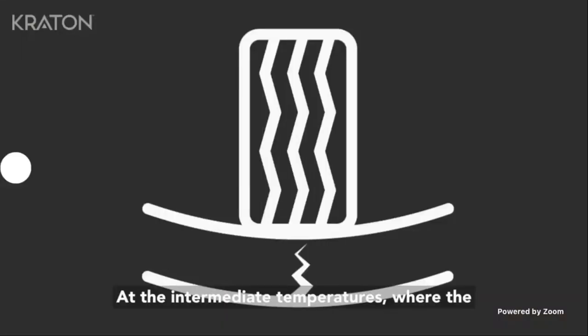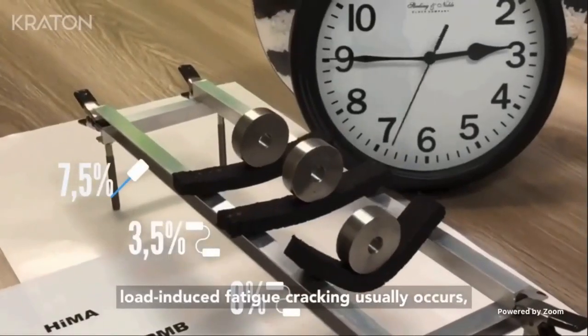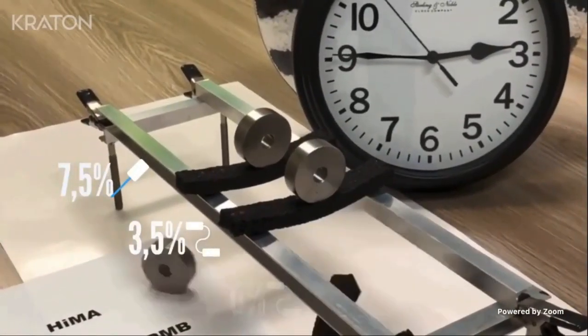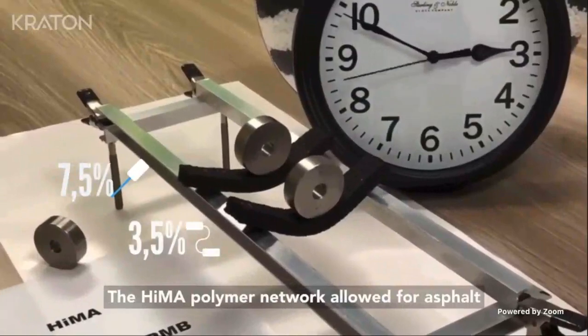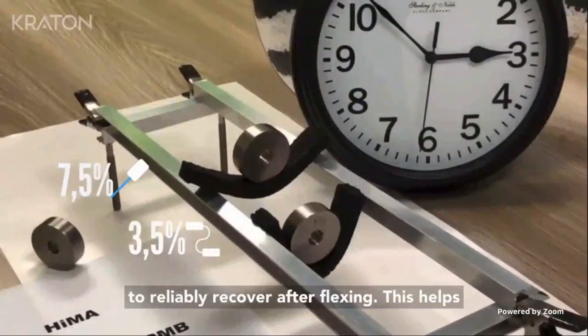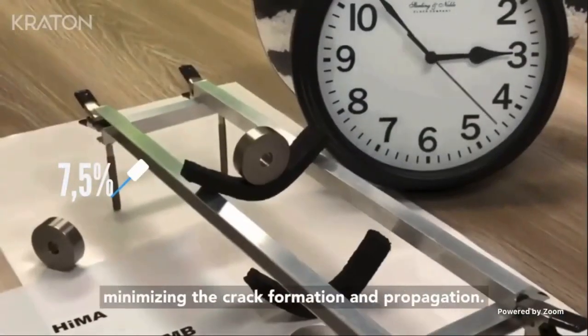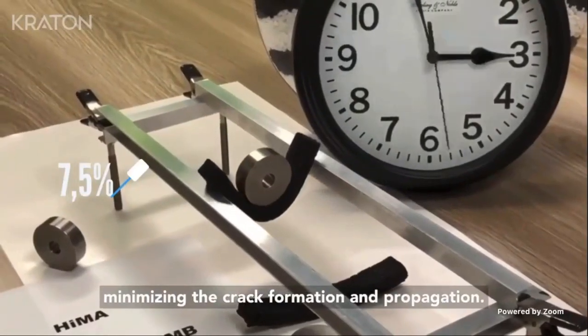At the intermediate temperatures, where the load-induced fatigue cracking usually occurs, the HiMA polymer network allowed for asphalt to reliably recover after flexing. This helps minimizing the crack formation and propagation.